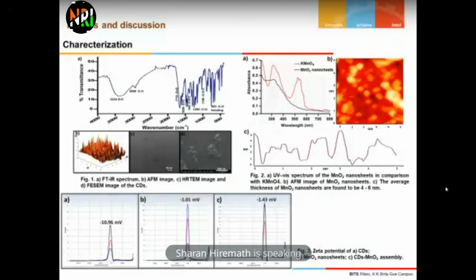And further, for the FRET, the carbon dots have to come onto the surface of the MnO2. That's why we have carried out the zeta potential analysis, where carbon dots show minus 10 millivolt and MnO2 shows minus 1 millivolt. On addition of CD on the MnO2, the zeta potential of MnO2 has just increased to minus 1.43. So this shows a successful formation of CD-MnO2 assembly.